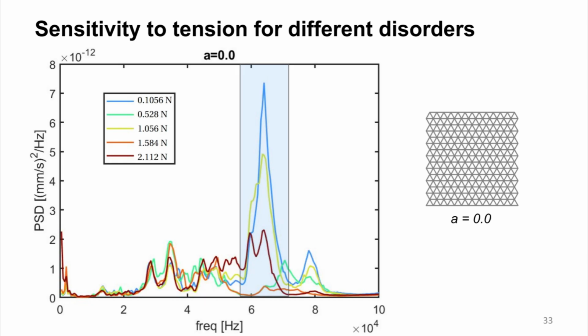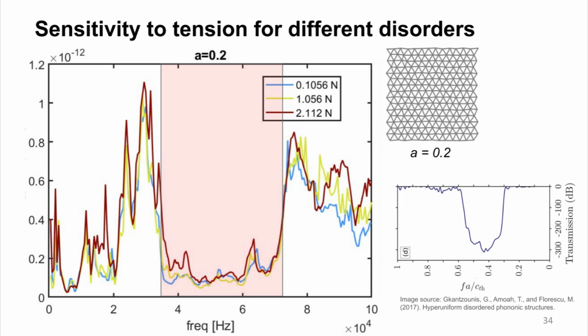So for the no disorder lattice, as I already showed, the Bragg peak has dependence on tension, and that's the primary feature that I see in the curve, which does have a non-monotonic dependence on tension. For the lowest disorder of 0.2, the lattice does not look very different from the no disorder lattice. However, I do get a wide band gap, and it is robust under multiple tensions I have tried here. I tried 0.1 Newton, 1 Newton, and 2 Newton of tension under which each spring was held. And I find that the band gap region or any of the other features around the band gap were not changed appreciably, and the band gap was not weakened by change of tension.